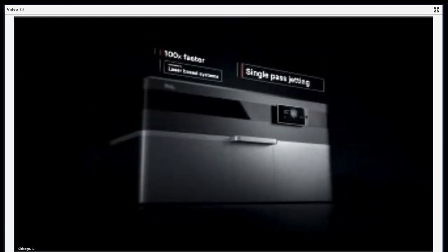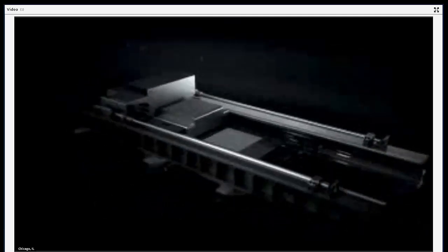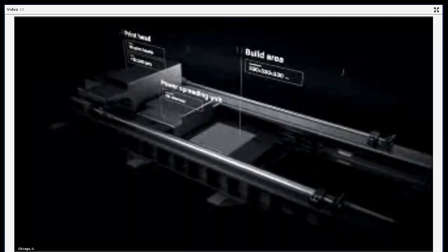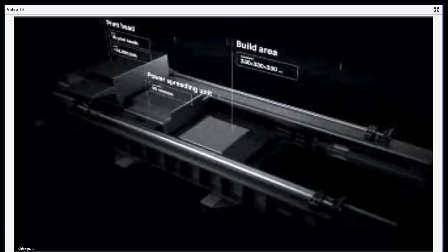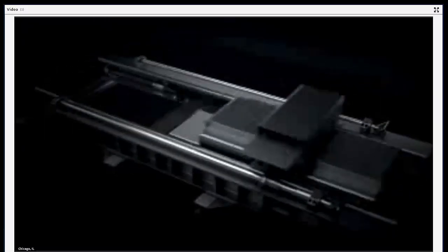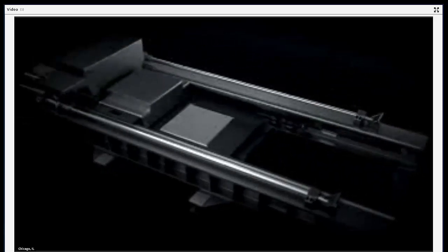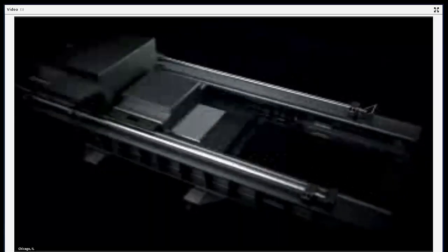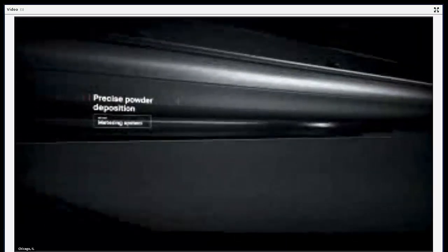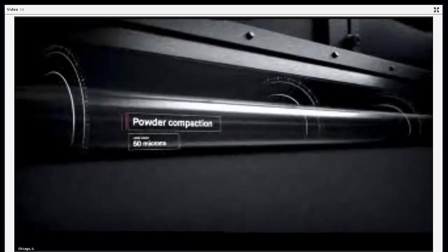It works by combining 2 powder spreaders and 1 print unit into a single pass system to both spread metal powder and print. Unlike existing metal 3D printing, there is no wasted motion with single pass jetting. A single pass starts in the powder spreader, where a metering system deposits metal powder, and a compacting system forms a layer as thin as a human hair. The print bar follows, jetting droplets of a binding agent. Millions are jetted per second, binding metal powder to form high-resolution layers.